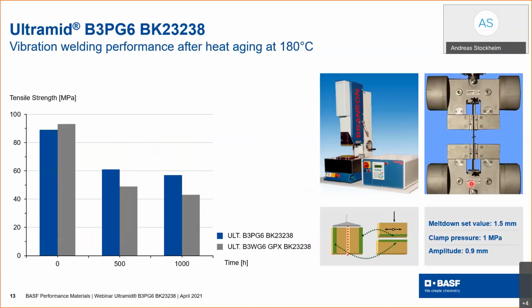For some of the applications we are looking at, vibration welding performance is important. That was also a target, to increase the vibration welding performance. And as you can see here, at 0 hours, the weld line performance is almost on the same level in comparison to the GPX. And after 500 and 1,000 hours, the B3PG6 outperforms the GPX in welding performance. After 1,000 hours, the difference is an increase of 25% in weld line performance.